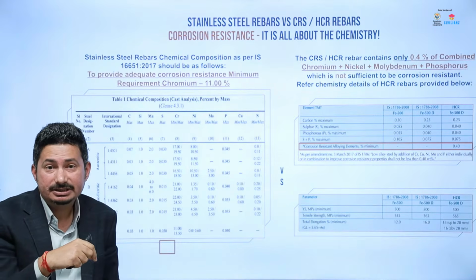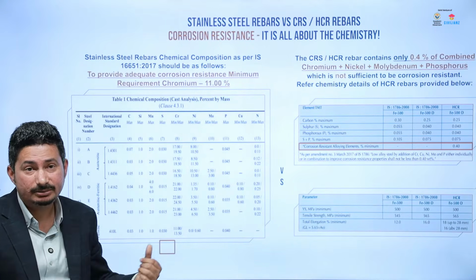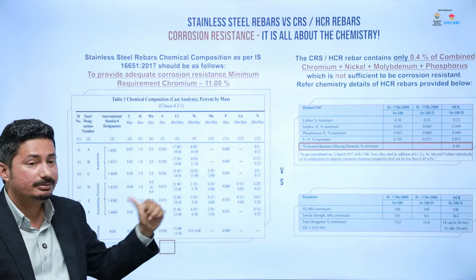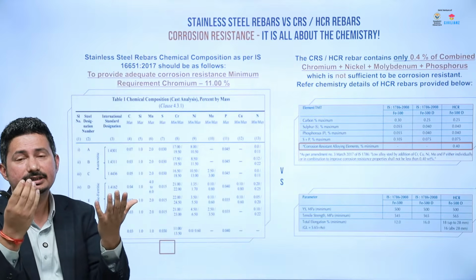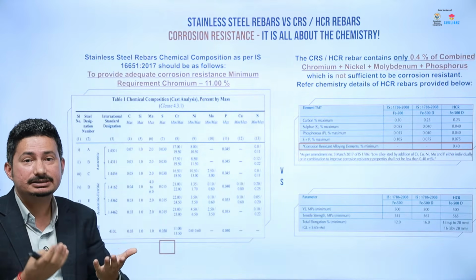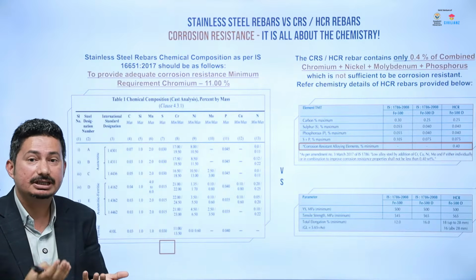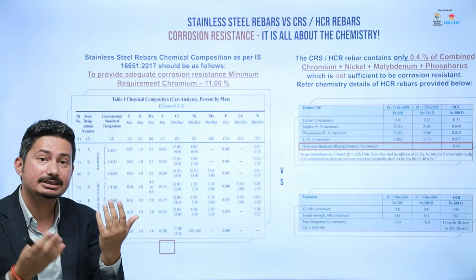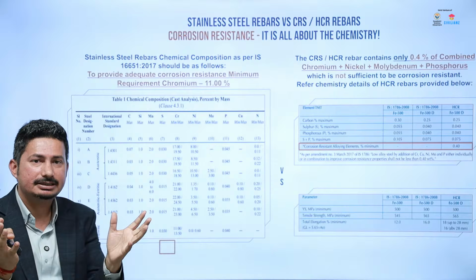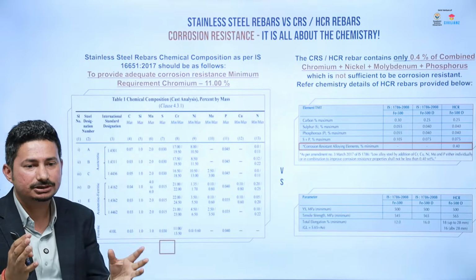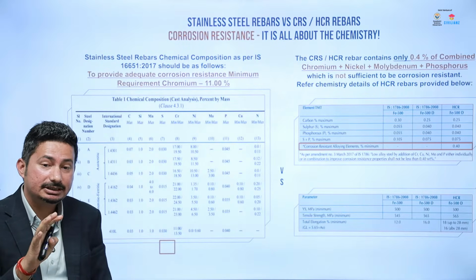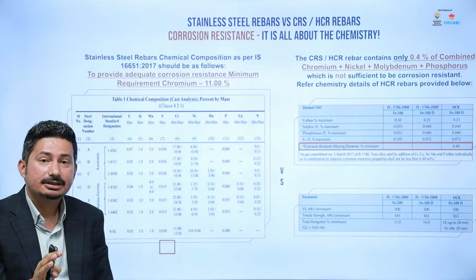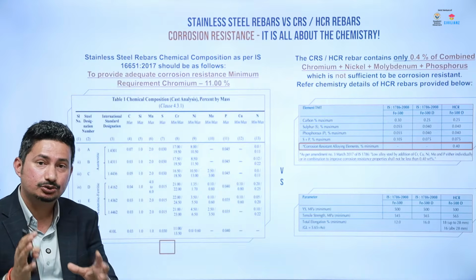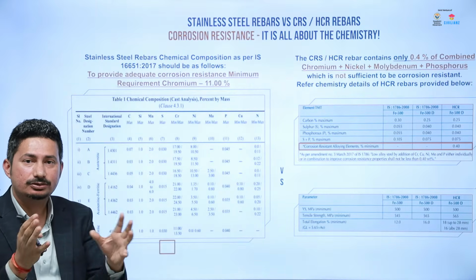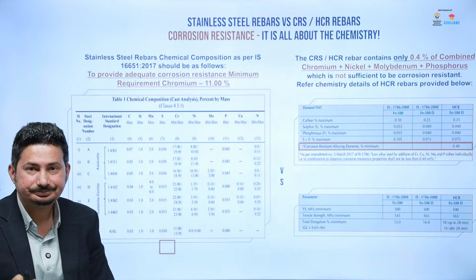Whereas if you compare with stainless steel rebar, in stainless steel a minimum of 11 to 13.5% chromium is present. So obviously the corrosion resistance capability of stainless steel rebar is much higher than CRS rebar. Generally, consultants have this notion that when corrosion resistance is the criterion to choose a rebar, most consultants go for stainless steel rebar.